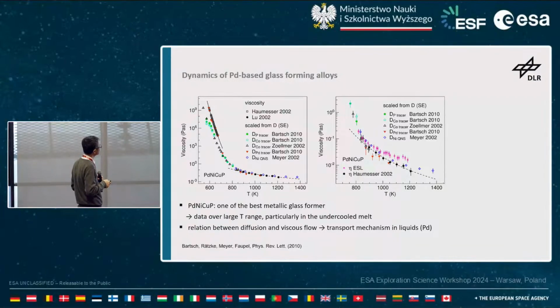What is interesting, especially in this region, is that palladium is a major component and it follows the trend of the viscosity, while the other small atoms, so phosphorus, nickel, and copper, are faster in the undercooled melt. So basically one has a split of the transport coefficients, but one can say that the viscosity of the melt is driven by the large atom, or by the majority component.